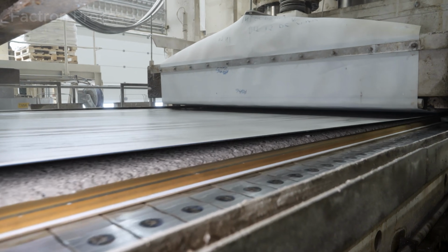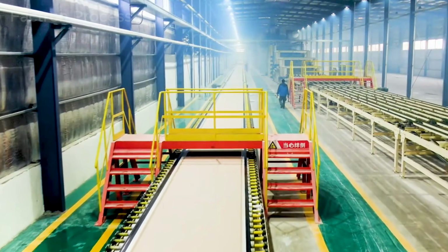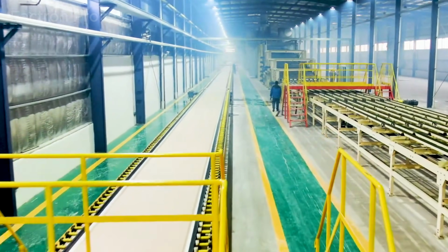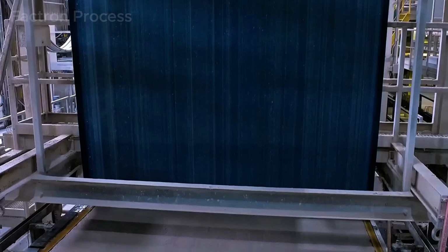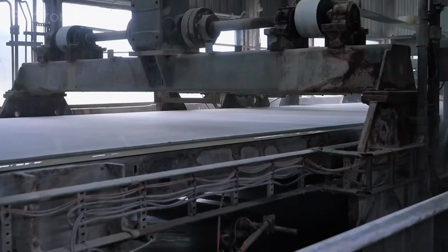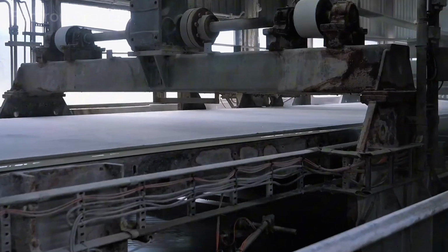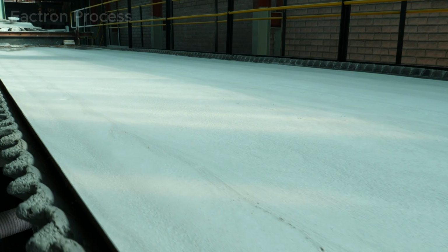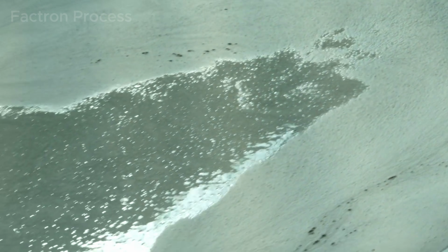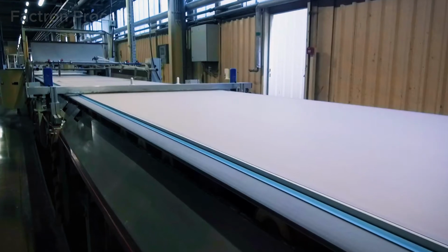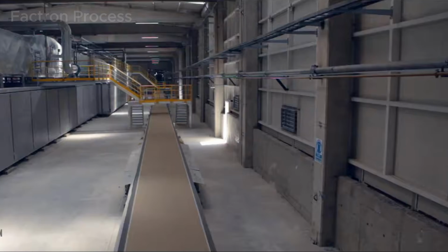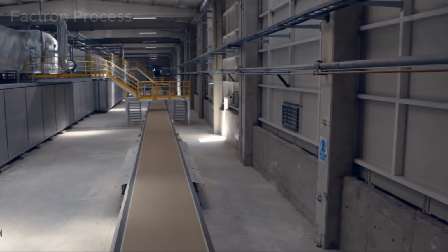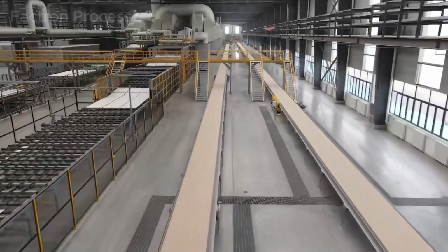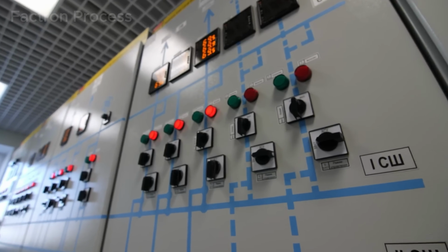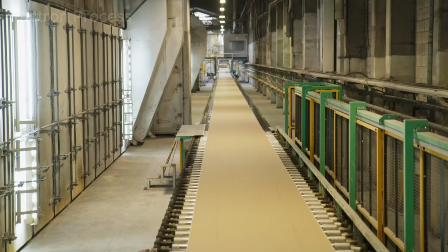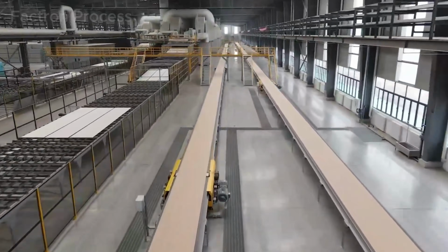The entire process is controlled by the chemical reaction taking place inside the gypsum core, not by any press or heating system on the production line. At this point, the reaction between stucco and water is still occurring inside the material. New gypsum crystals gradually form and interlock with one another, causing the thick white slurry to begin turning into a solid mass. The drywall panel becomes firm enough to hold its shape and continue moving along the conveyor without deforming. This is the first moment when the product truly takes the form of a finished drywall panel, even though it still contains a large amount of water that must be removed in the next stage.